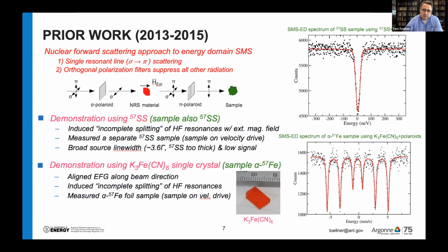So we use cross polarization filters. By cross, I mean they're orthogonal. So we have a sigma polarization filter and a pi polarization filter. And then in between them, we put a resonant material. This is a material that is optically active within a resonant band. And so the cross polarization filter suppresses all the non-resonant radiation. And the nuclear resonant material introduces some polarization switching just in the resonant bandwidth. And so one can get a spectrum that is just of gamma rays out with some small background.